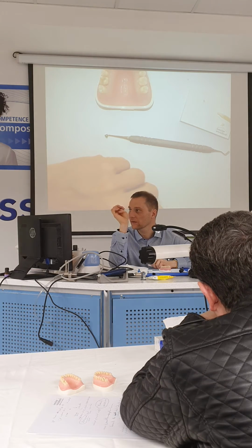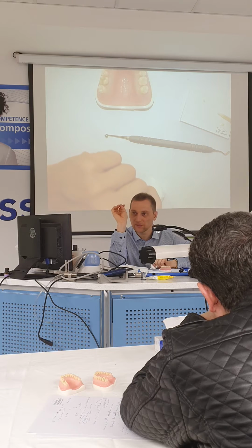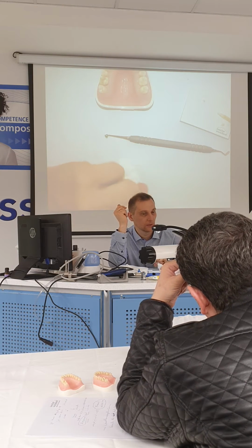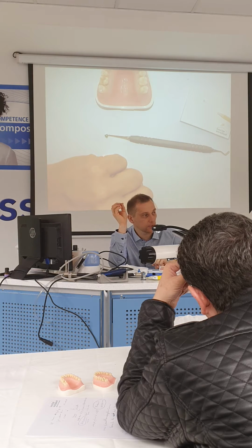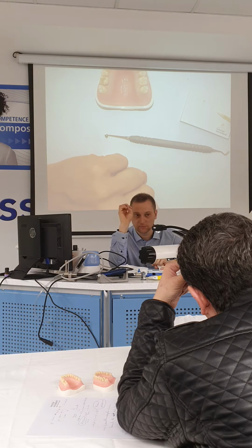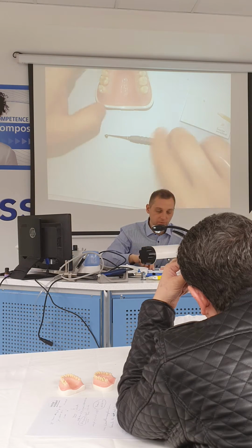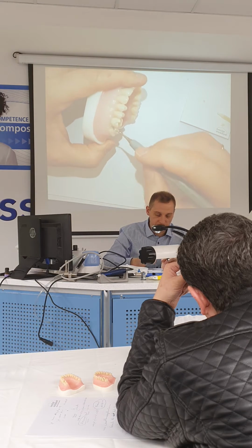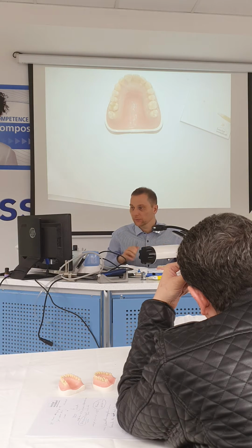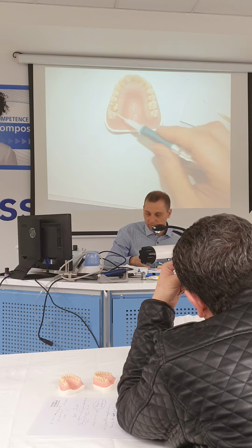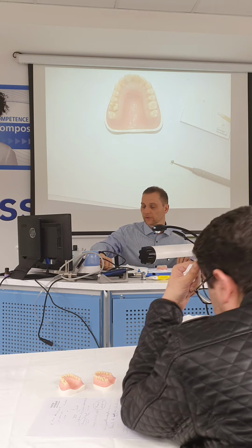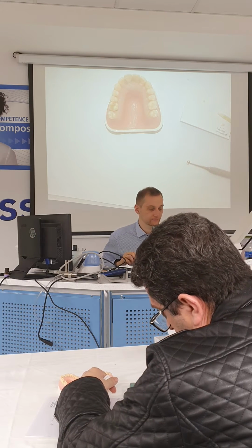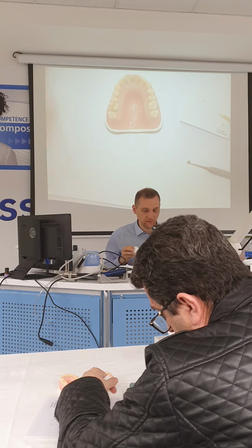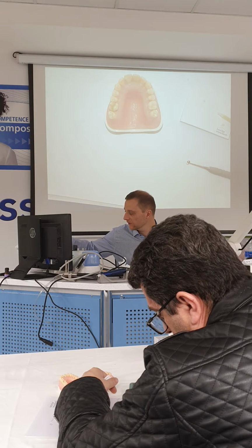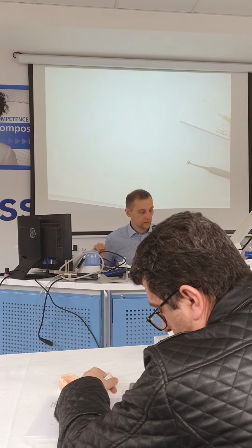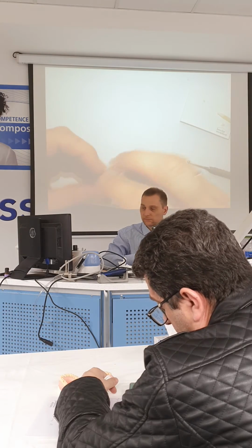Despite we think that we have removed everything, it might happen that you still have just a little bit of the adhesive, which can be removed by polishing. And if you use the articulating paper, you can see it better, where the material is still available. But of course, you have to do it also for the cervical margins as well. Good, so after the removal of the excess, the same procedure we have to apply liquid strip, light cure completely, or we can wait for 5 minutes approximately until the material will be set. We can just skip this step because this is nothing special, completely the same like we did for anterior crown and the veneer.